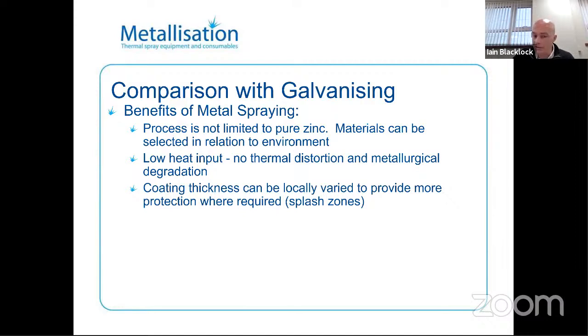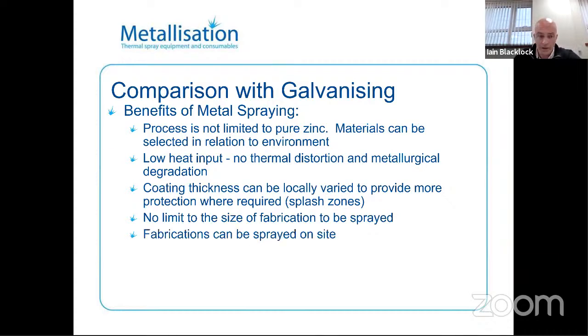Coating thicknesses can be locally varied. So on a structure, if you have more corrosion at the base, you can apply a thicker coating to the base and a thinner coating at the top, rather than with galvanizing, which is a uniform thickness all over. There's no limit to the size of fabrication that you can spray. And the fabrications can be sprayed on site. So instead of having to move something to a galvanizing bath, it can be done in your own yard. It can be done in your own spray shop, potentially.